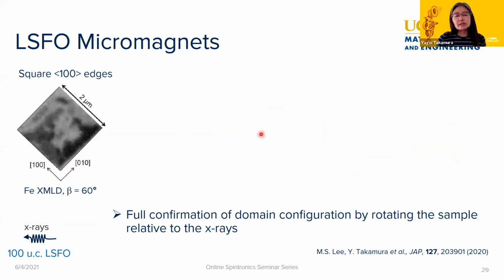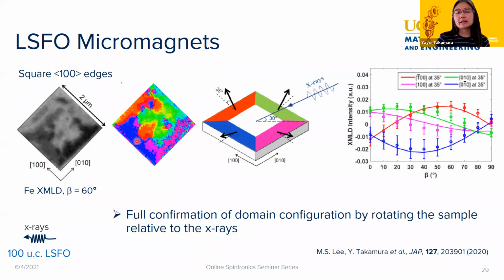And what we did, just to confirm that we have made the right assignment of our antiferromagnetic spins, is we rotated the sample by 45 degrees and then repeated the experiment. And again, we're able to bin our 4 different types of domains, again showing that we have this preference for these different colors to lie along the edges, right? So using that, we have this shape anisotropy.